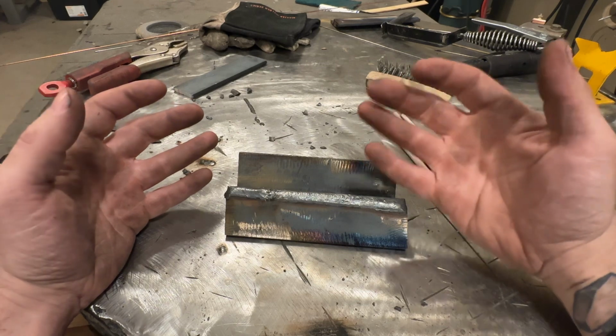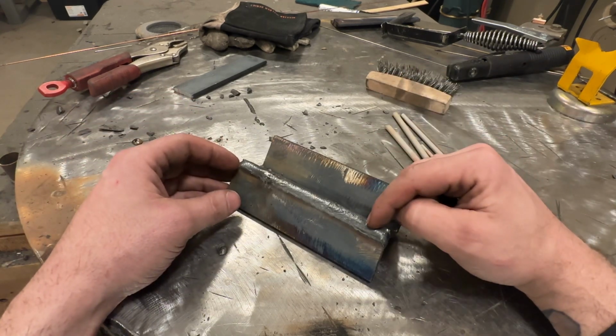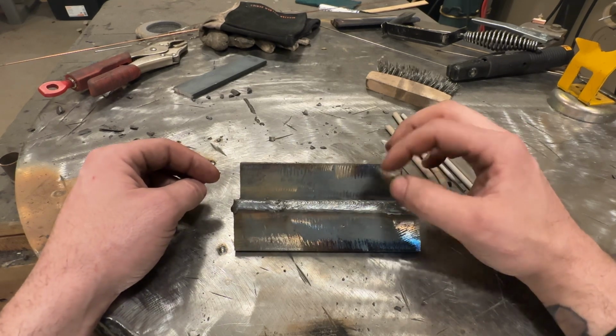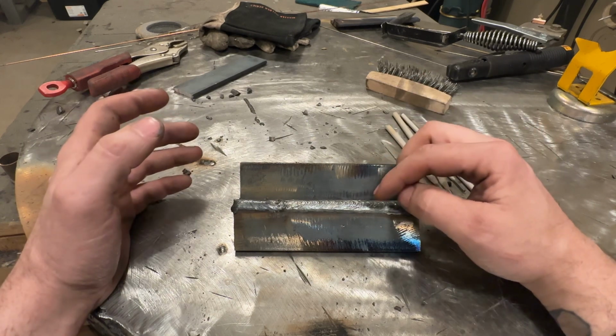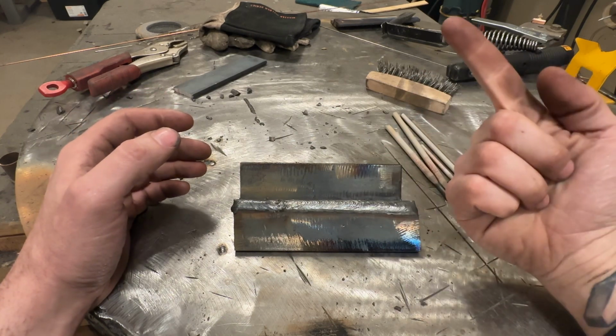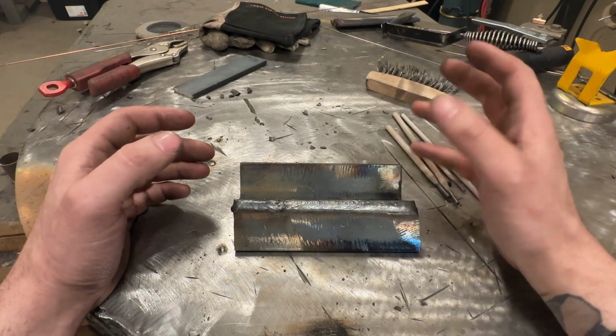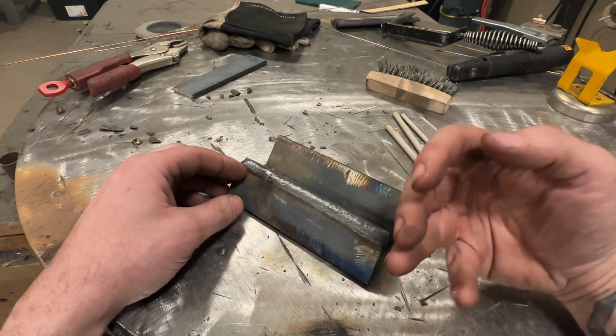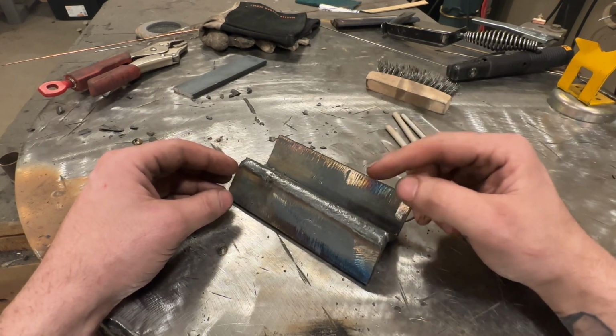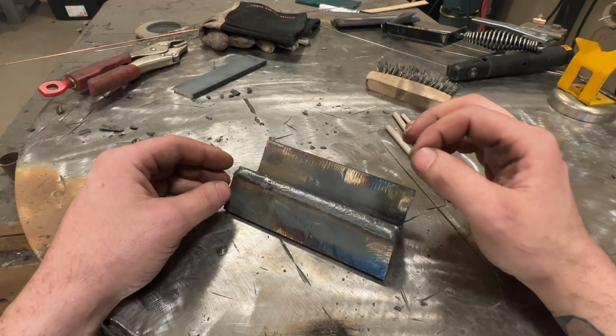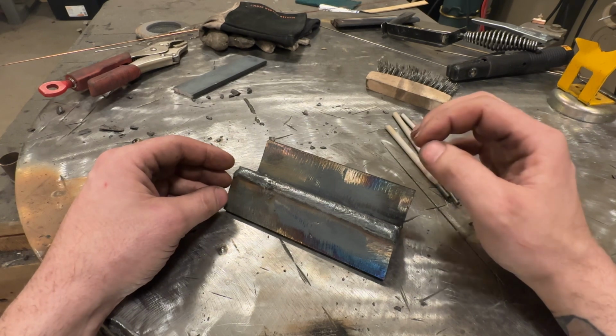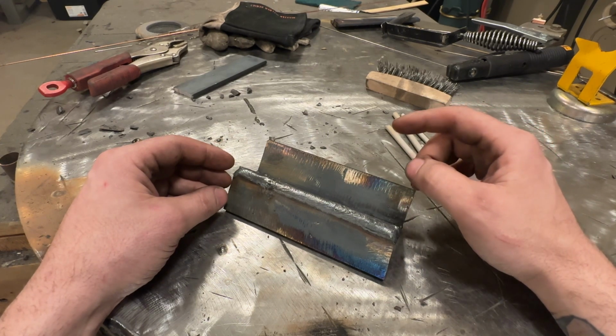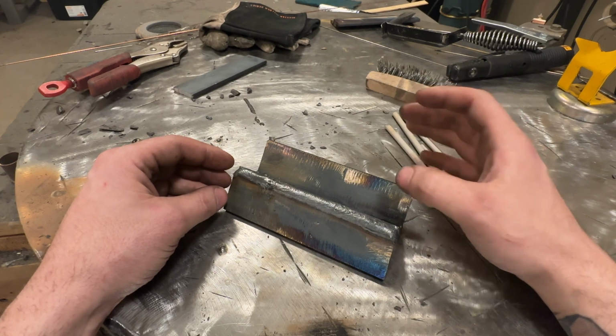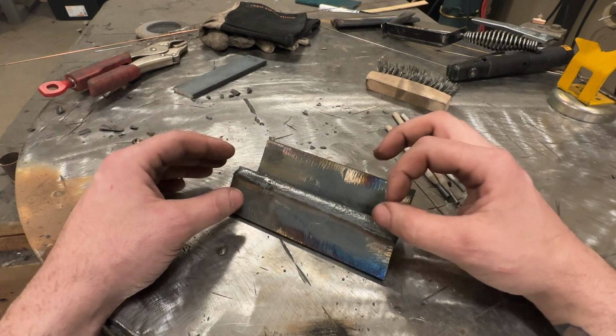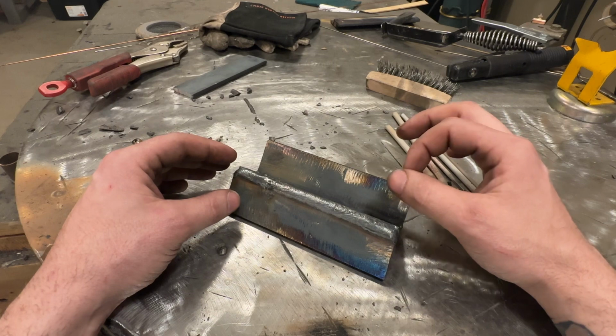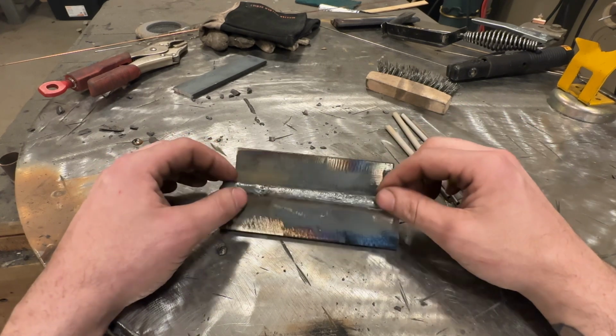Now, for us home gamers, most of this is somewhat irrelevant. I mean, is this going to be weaker than that 1/8 inch pass on the other side? Arguably not really. The bigger issue for us at home is really going to be, does it have porosity in it? Does it have lack of fusion, undercut? Those are bigger defects for us than the difference in grain structure. But I'm giving you this information for free, mind you, just so you can think, hey, if I'm welding something critical that needs absolute strength, should I do multi-pass or single pass? And if you want the better strength, a single pass of a really big weld, odds are, will destructive test worse than a 2 or 3 pass weld. It's something to think of.